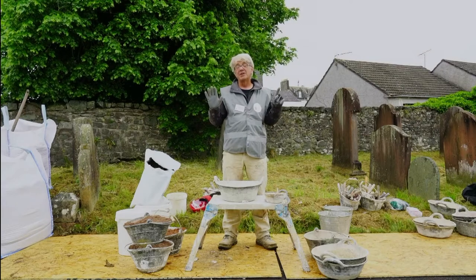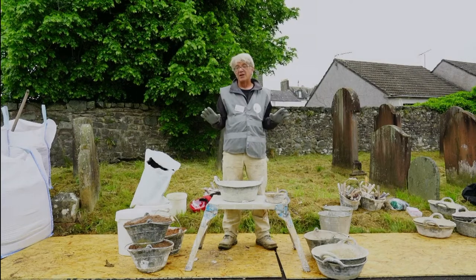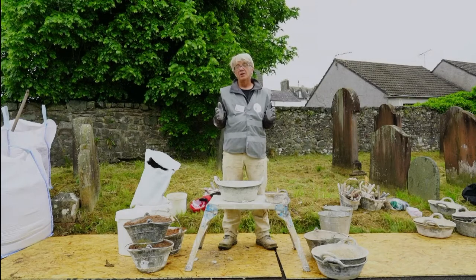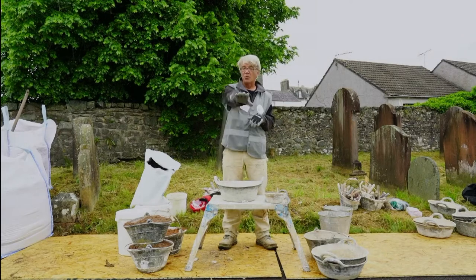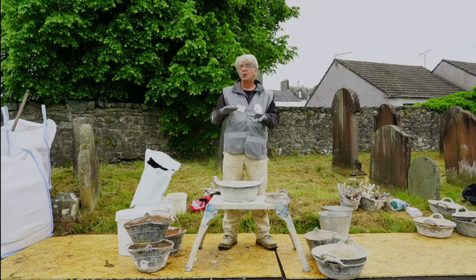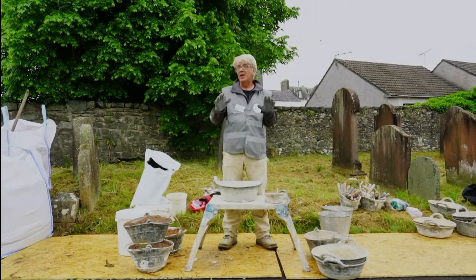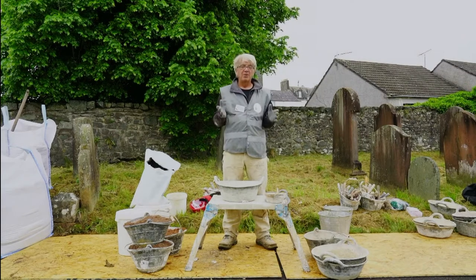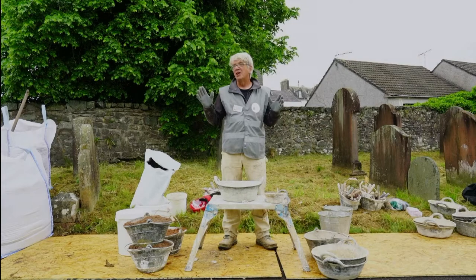The United States Bureau of Standards back in the 1920s and 30s looked intensively at mortars, for reasons I'll talk about later. But the one mortar that they said was the worst possible mortar that you could build a building with, from every angle, from the angle of workability, from bond, from its tendency to let water straight through the wall because it doesn't form a proper bond, the tendency to expand and contract whenever it gets wet, and therefore break whatever bond it made. We all know this, cement comes loose on an old building, because it expands and contracts every time it gets wet. A little bit, but a little bit is enough.